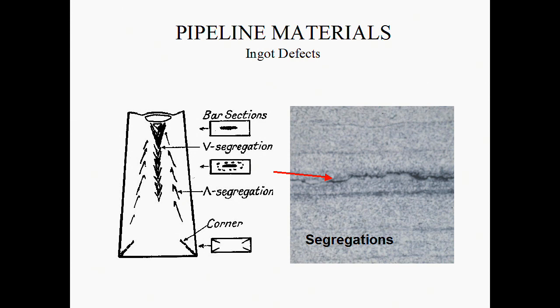So that mould is wider at the bottom than it is at the top, so you would end up with a segregation pattern that points inwards towards the middle and top of the system. So what's segregation? Well, in the steel making process, you have molten iron, but it has things like sulfur in it and oxygen, and manganese is added in the steel making process, so you get things like manganese sulfides and manganese oxides and iron oxides that are trapped within the material. And if they were kept in the liquid phase long enough, they would float up to the surface because they're less dense than molten iron, and then they're scraped off in a slag layer.